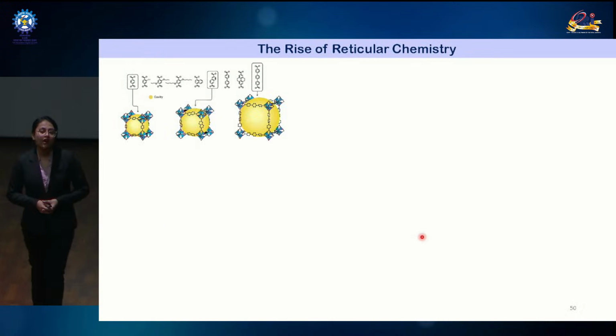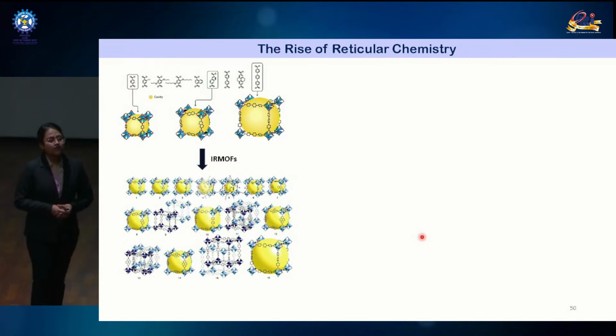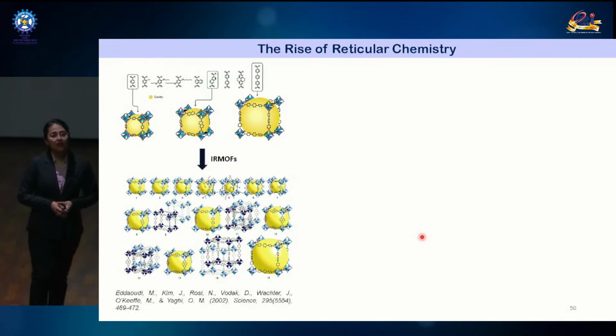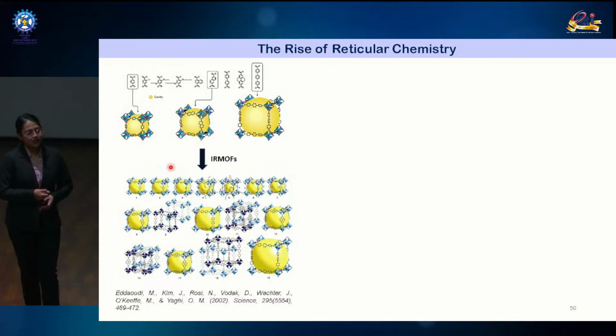This very idea of designing MOF-5 eventually led to the tuning of the framework. Here we can see that this is the structure of MOF-5 where the organic linker was tuned. That is, it was changed. Simply the length of this organic linker changes. That eventually led to the designing of 16 different variants of MOF-5, both having larger and smaller cavities.